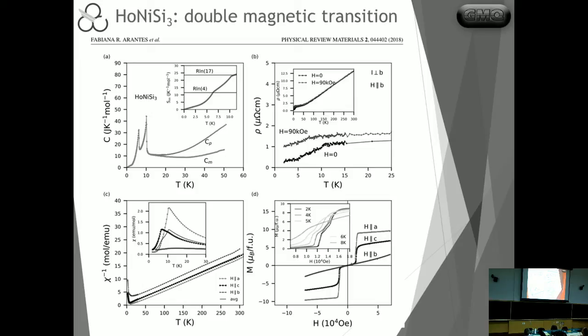And holmium is moving in the direction of a shift from the A-axis, easy axis, into the B-axis, which we had seen from terbium. Since holmium is right there in the middle, it actually shows some pretty interesting anomalies here. What we see in this case is that there are two different ordering temperatures. So these two transitions are related to two different Néel temperatures related to two different directions.